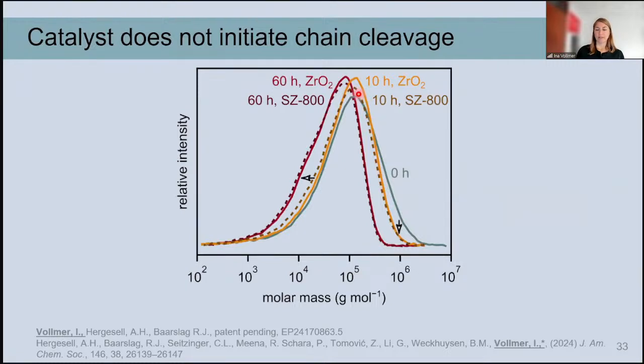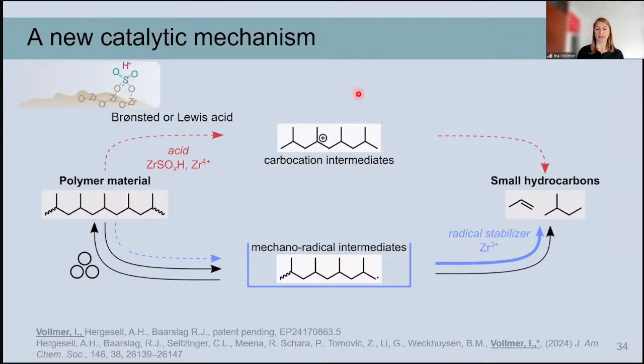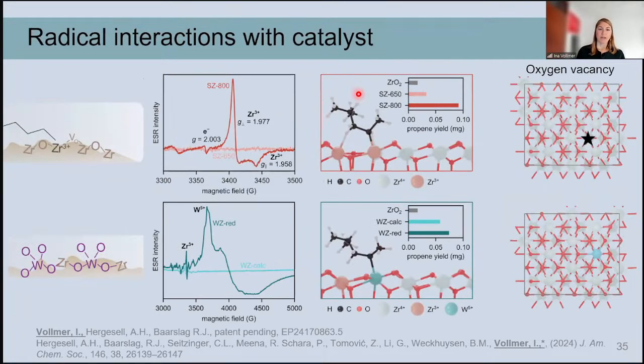And because the molecular weight is changing, so we see a lower molecular weight because we have the carbon-carbon bond cleavage. However, we don't see more cleavage when we add the catalyst. So this to us indicated that we are not seeing more initiation of the radicals, but actually we have to look at the second part. So we're not looking at the radical initiation, but we are looking maybe at the radical stabilization. And so what can stabilize radicals? Something redox active. So we tested with electron paramagnetic resonance spectroscopy whether we have unpaired electrons on our catalyst that could somehow interact with radicals.